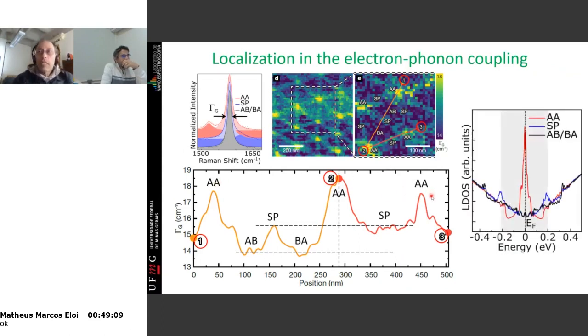And this is related to the electronic structure of the system, because the AA location has a strong electronic density of states at the so-called neutrality point, at the Fermi level of the undoped material. This generates a lot of electron-phonon scattering. The phonons are killed, so the lifetime decreases and the energy uncertainty increases. These strain solitons also have peaks here, and this energy is exactly the phonon energy, so they also like to kill phonons. And then you can understand all this in terms of the phonon lifetime.